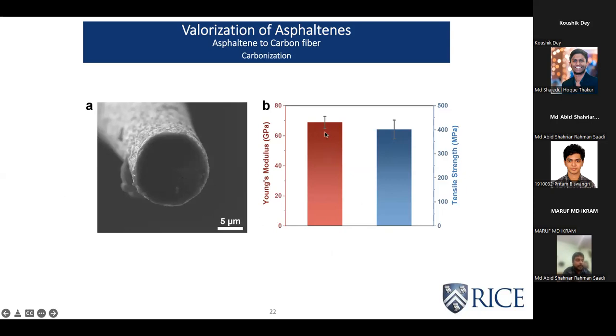We reached Young's modulus up to 70 gigapascal, and the tensile strength was around 400 MPa, which is not the best, but if you consider that we are making these carbon fibers from a waste material, and this is one of our first attempts in making carbon fibers from this waste material, I think this is a pretty decent number. The commercial carbon fibers typically have a strength from 1 to 10 gigapascal.